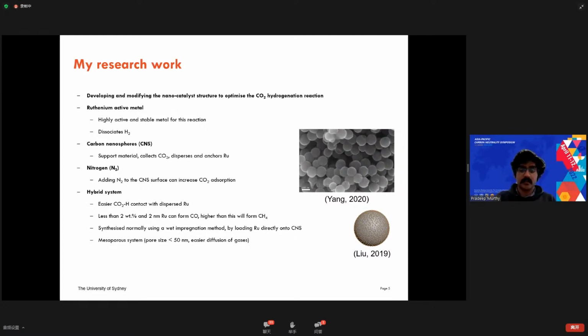These catalysts were synthesized using a wet impregnation method by loading the ruthenium onto the carbon nanospheres, resulting in a mesoporous system, which based on literature will enable easier diffusion of the gases passing through for the reaction.